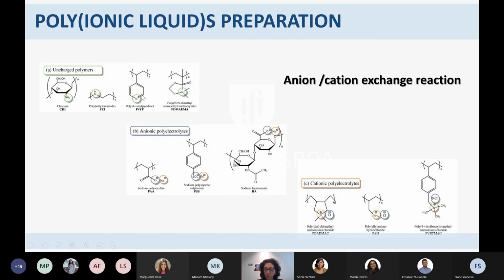So how do we do it? We have either uncharged polymers, or anionic polyelectrolytes, or cationic polyelectrolytes. If we have uncharged, we just functionalize it. As I told you, we make an alkylation in these groups that are here. If we already have anionic or cationic polyelectrolytes, we just do an anion exchange. So we just replace, for example, this sodium with the NTf2 anion.